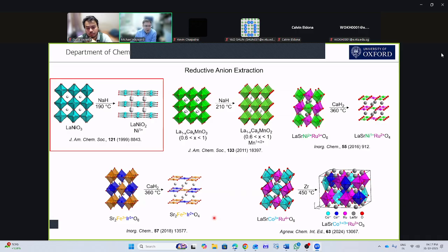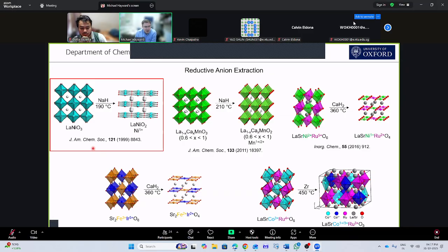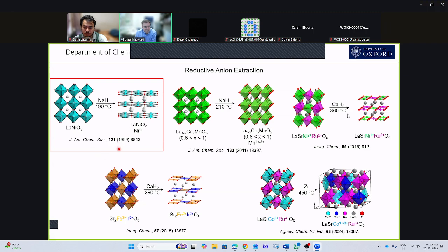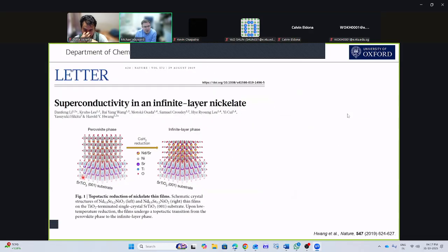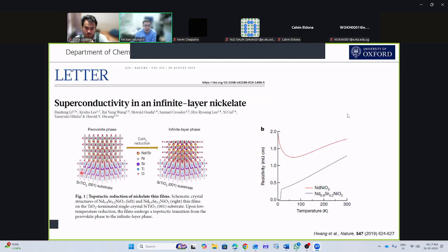I'm actually going to focus on this one here. This is the material where it all started, making this compound. And you can see this was done quite a long time ago, 1999. But 20 years afterwards, a group in California run by Harold Hwang basically took this chemistry and put it onto a thin film. And what they discovered, and it had been widely predicted for quite a long time, is that if you put this material on a thin film, you can make a superconducting compound.